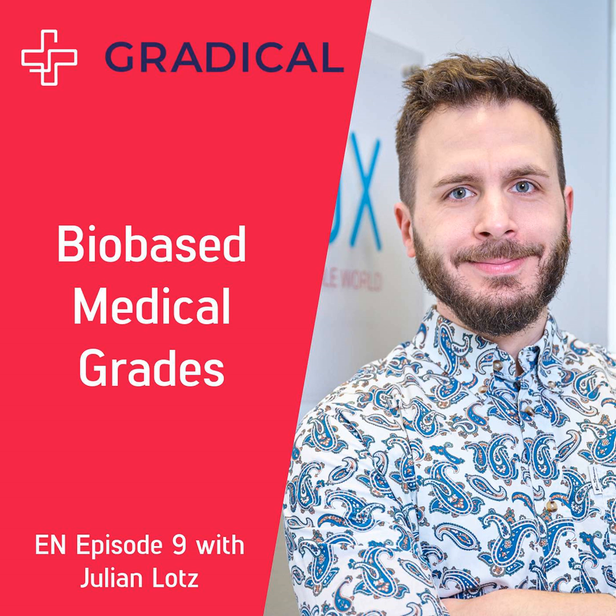Not in the high performance plastics, but for example, if you look at PEF, which is more or less a fully bio-based derivative of PET using a furanate instead of a terephthalate, there you have even better properties when it comes to barrier properties, which is quite important, of course, for the relevant applications. And the production of those monomers, FDCA, for example, can be more energy efficient than the production of PET. There is also a lot of research currently ongoing in there, but that's also an example where you maybe could find similar polymers that are more energy efficient in production, not only through incorporation of bio-based carbon, but also through quite efficient processes.